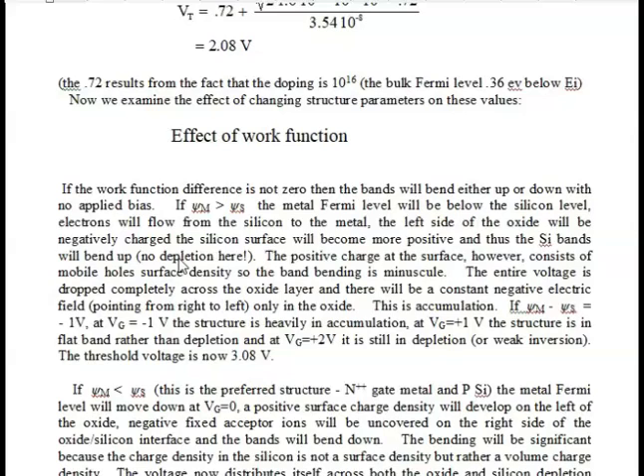Okay, now let's look at the effect of work function on all of this. So if the work function is not zero, the first case we considered the work function difference was 0. So now we're going to consider work function difference not equal to 0. And we start with the non-ideal case or non-preferred case where the metal work function is greater than the silicon. Of course, in that case, as we've said a number of times, if we have equilibrium, we will be in accumulation. At minus 1 volts, we'll be even more in accumulation.